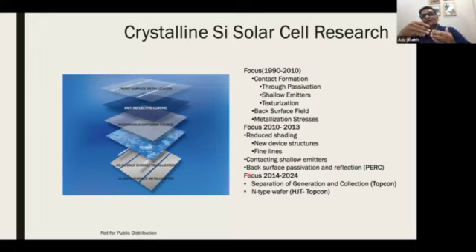If your carrier reaches the backside, wherever metal comes in contact with semiconductor, it creates a lot of traps, and that is a destroyer of the carrier. So somehow you need to have a scheme where your carriers are protected from this, because the aluminum used to cover the entire backside. And you still have the bus bar which can carry the current, but if you reach the backside, then you would have a recombination. And so P plus back surface field reflects back the carriers, and it helps in reducing the recombination. I have some data which I will show you.